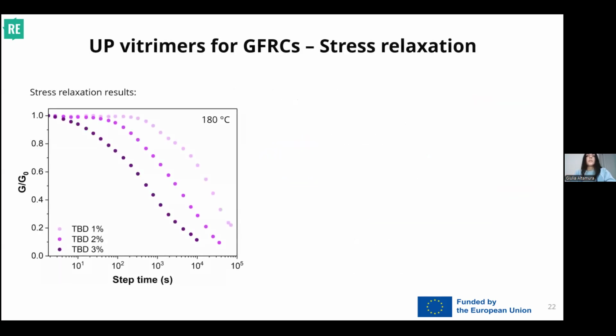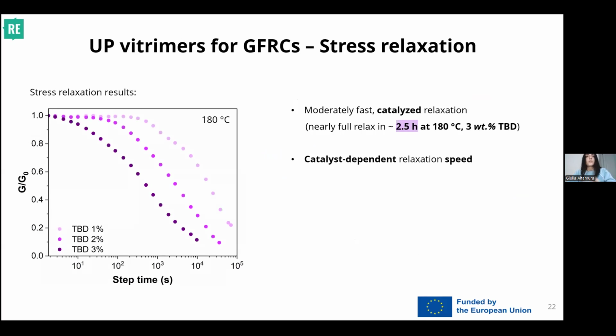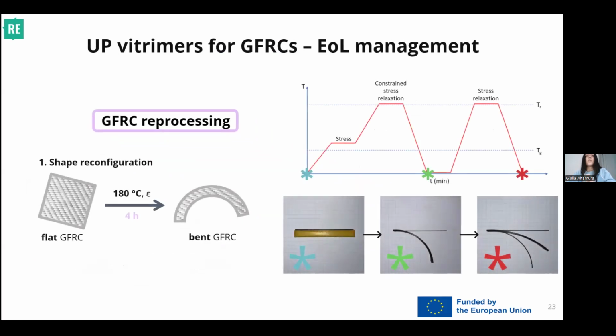Together with it, we also added a transesterification catalyst to help with the exchanges. So as we can see, also in this case, we have a vitrimer because stress relaxation could go down. And we also see that the higher the catalyst content, the faster the relaxation. In this case, actually, relaxation was not really, really fast, but was acceptable. With this matrix, we produce a glass fiber reinforced composite that, also in this case, was reprocessed with shape reconfiguration, as in the case before.